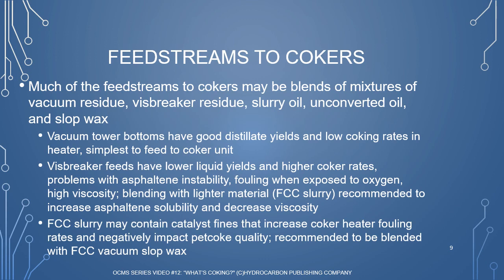FCC slurry oil, on the other hand, may contain some amount of catalyst fines even after being subjected to a solids removal process, and these fines can increase coker heater fouling rates and negatively impact petcoke quality. Vacuum tower slop wax is generally recommended as a blending material as it will contain some amount of distillate depending on the operation of the vacuum tower.